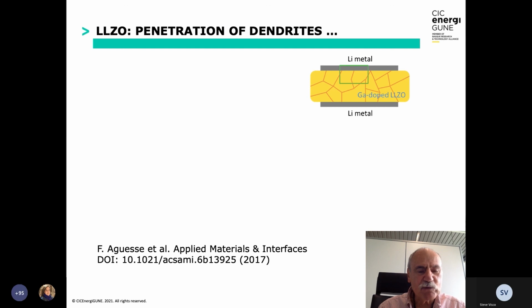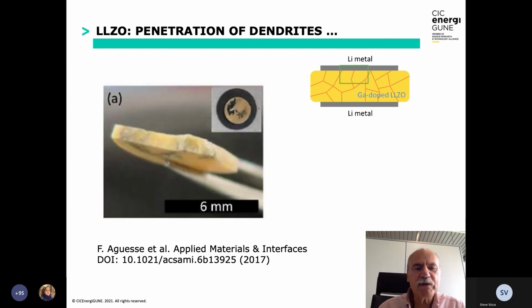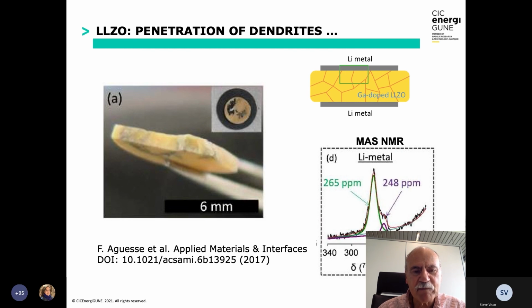The problem with LLZO is that they are not very resistant to dendrites, the needle type formation from the negative electrode on recharge, which can pierce the electrolyte and make a short circuit. If you make a test between lithium metal sandwiching zirconium garnet, you can see that immediately, after a couple of hours of operation, your garnet type is like blue cheese, and the blue veins are in fact metallic lithium, as can be shown by the NMR, solid state NMR. You have lithium which has been growing inside the ceramic at the grain boundaries.